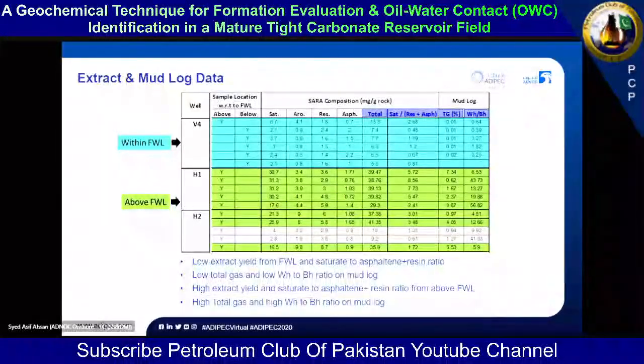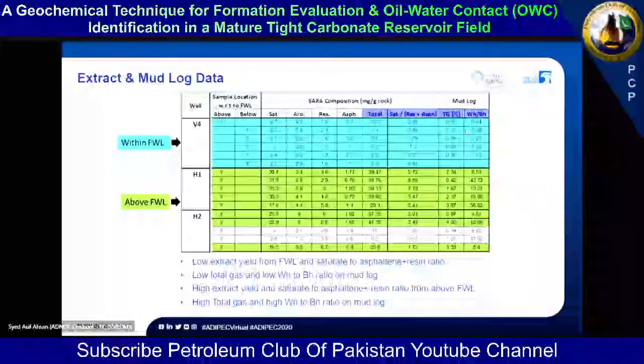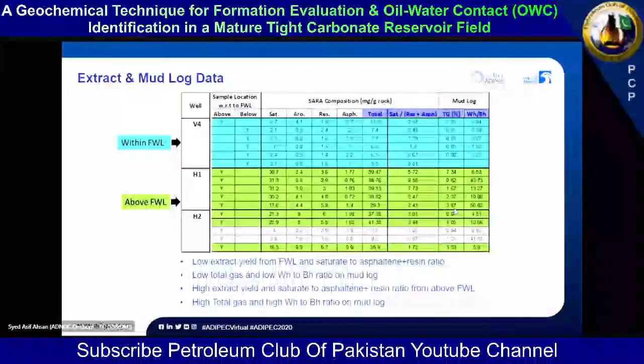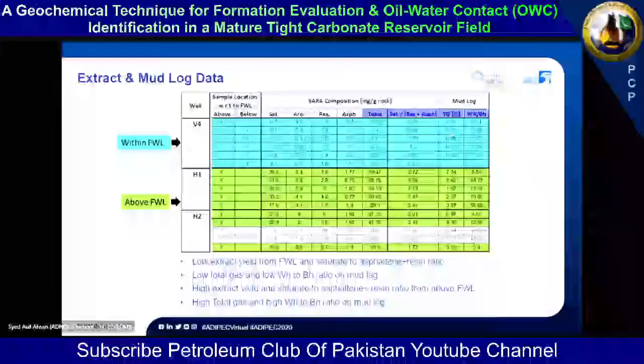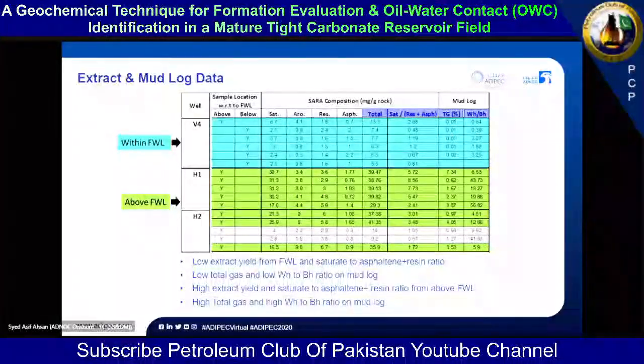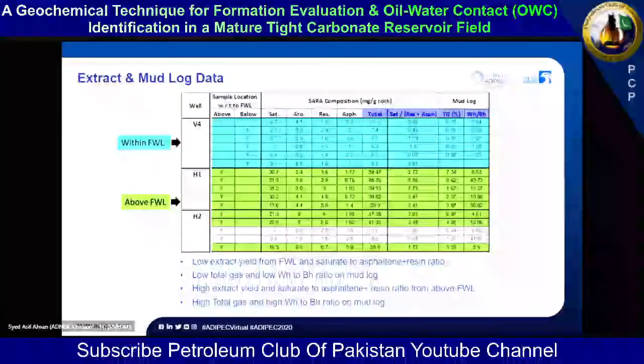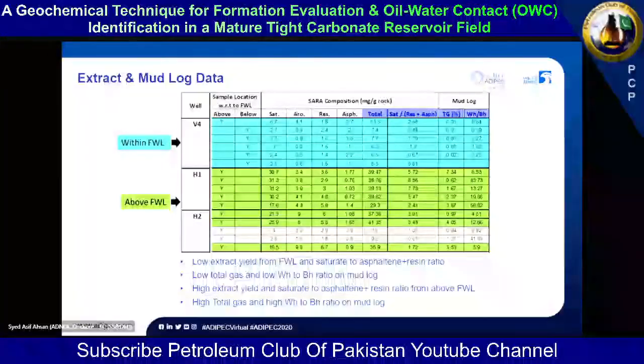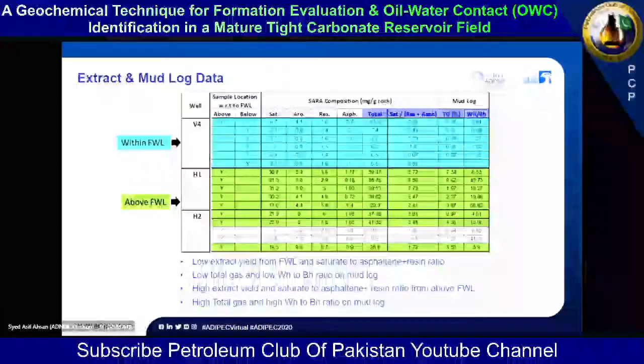And their saturated to aromatic ratio for a sample coming from the proper oil column is much higher than the samples coming from the free water level. Again, from the mud log also, you are seeing high total gas readings for samples coming from the oil column, and samples coming from the free water level have very low total gas readings from the mud log. And their wetness to balance ratio, wetness is also a ratio, and balance is also a ratio, but it's a ratio of the two ratios. And to appreciate, when the ratios are higher, you're talking about oil, and when the ratios are low, you're talking about a non-producible zone, maybe with some dissolved gas in it. Okay.